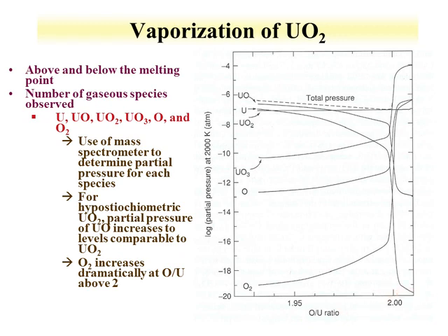And the reason that that's important, if you think about when uranium fissions, the fission products are going to want to form oxides. How much oxygen is available will dictate which fission products can form oxides, and as we'll learn when we evaluate the chemistry of fission products in spent fuel, we'll see that some metals, such as the metals from molybdenum up to palladium, form metallic inclusions.